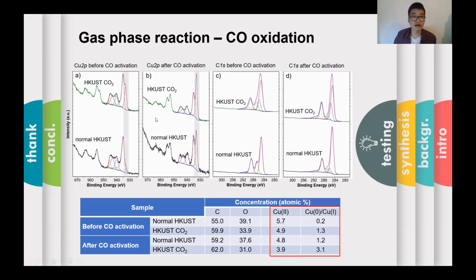After CO activation, both samples show an increase in the low valence copper content, confirming the reaction of CO during the experiment. And the new carbon-oxygen bond containing species in the carbon signals for HKUST-1 CO2 confirm the defects which were revealed previously in this sample. However, we can still see that the majority of the carboxylic species remain intact, allowing us to make a fair comparison of the catalytic performance of these samples.